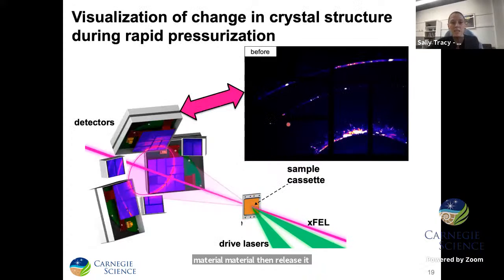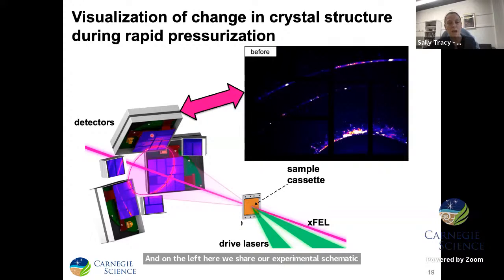So this video here shows a collection of X-ray diffraction images that were taken for one such series of shots where we shocked our silicon carbide samples up to a pressure slightly above 200 GPa. On the left here, we show our experimental schematic. From this, you can see that in these experiments, we're actually using 6 2-dimensional detectors, which are positioned about the incident beam in order to collect maximal scattering data. However, in this video on the top, I'm only showing this top detector.